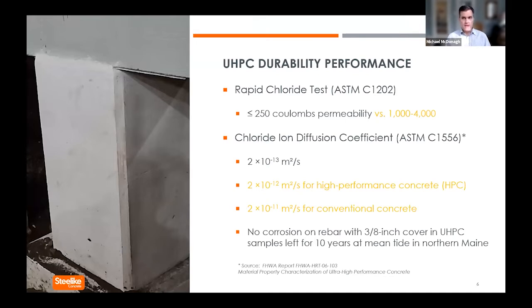Durability is where UHPC really shines. There's a number of ways to measure the durability of cementitious products. One is a rapid chloride test. UHPC class material is considered to have a maximum of 250 coulombs. Steel-Like and other products, some of them go as low as 50 coulombs versus 1,000 or more for conventional concretes. Or if you look at a chloride ion diffusion coefficient using some rounded numbers, we're looking at about 10 times the smaller coefficient versus high performance concrete, and about 100 times smaller versus conventional concrete.